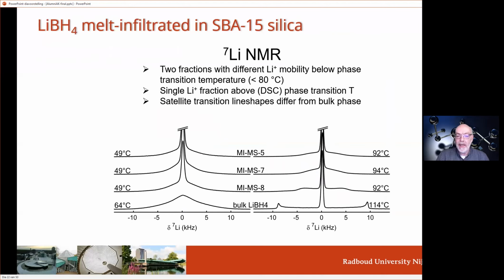So we looked again at the lithium spectra. And I showed you already the spectra of lithium BH4 in bulk, just the bulk matter. We have the low temperature phase, we have the high temperature phase. There is only one lithium site, but they have very strange spectra, as you see. There is a central peak, but there are also these broad features.